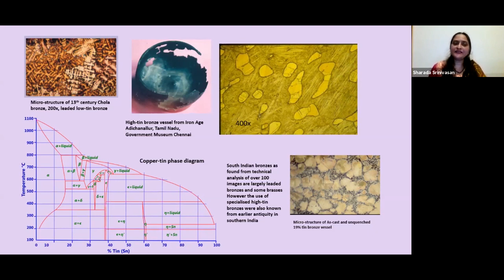But the interesting aspect is that the artisans had found out that when you take a bronze of 23% tin, and heat it to a very high temperature between 600 and 700 degrees, as you can see in that phase diagram, which basically indicates what happens when you keep adding tin to copper at different temperatures. So between this temperature range, 600 to 700 degrees centigrade, 23% tin can actually be forged very extensively due to the presence of this metastable beta phase. And somehow these artisans had been able to empirically arrive at this.